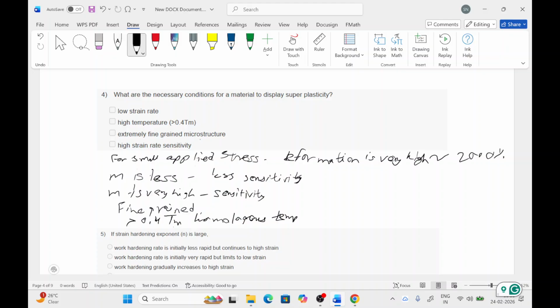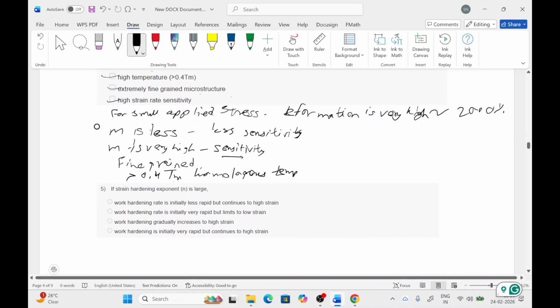Yeah, equiaxed also. Fine equiaxed grain size. And also we have a very high strain rate sensitivity. So we don't have to increase the strain rate much; at very low strain rate values we can achieve high strain rate sensitivity because the m value is very high. So for superplasticity, we require low strain rates, high temperature, extremely fine equiaxed microstructure, and high strain rate sensitivity. So all options are correct for the necessary conditions of superplasticity. Okay, so can we move forward to next question?